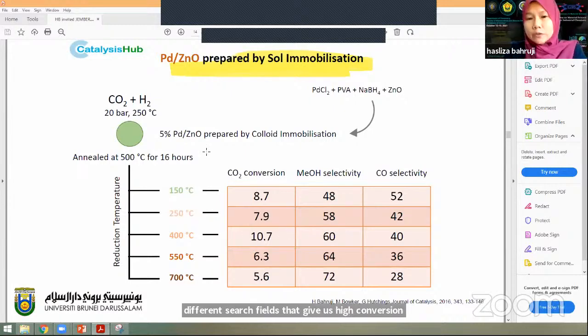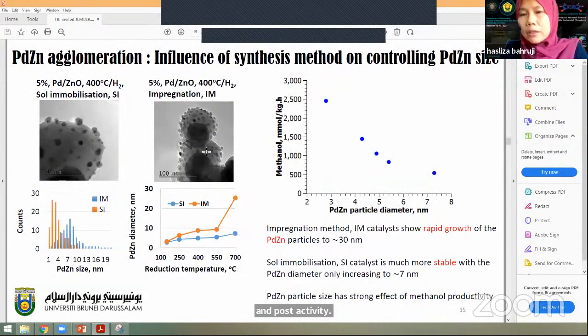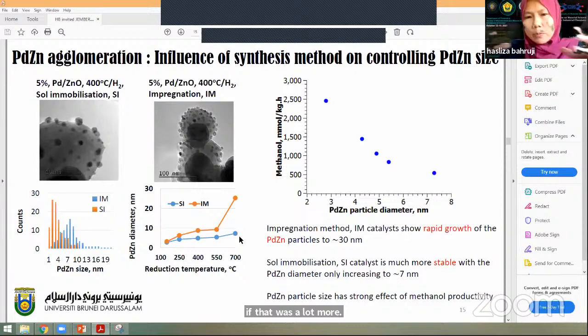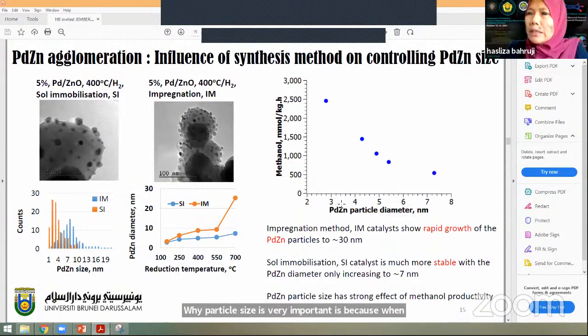And then when we investigate the influence of synthetic method to control the palladium zinc particle size, we compare the catalyst prepared using the immobilized impregnation method with the sol immobilization method. We can see that the agglomeration or sintering effect was a lot more negligible, and we cannot really see enlargement of the particle size when we produce the catalyst using sol immobilization. Why particle size is very important is because when we manage to control the particle size to be very, very small, we will ensure the catalyst has high productivity towards methanol.